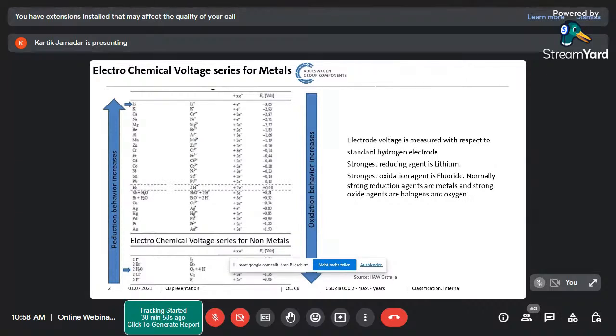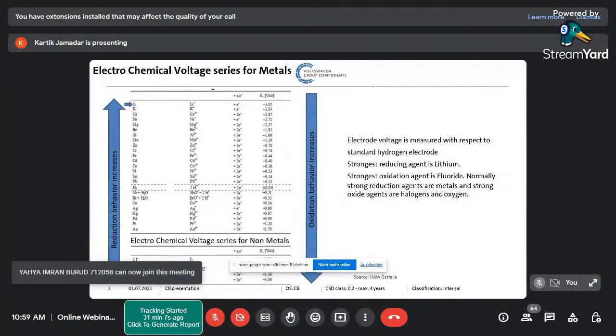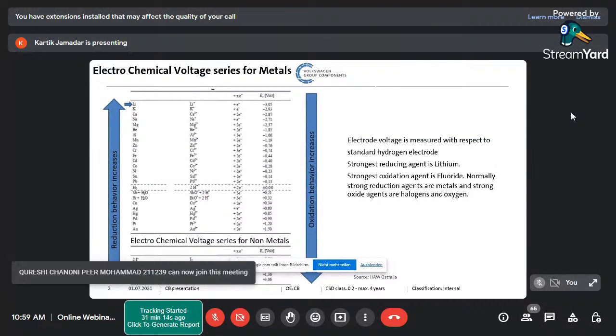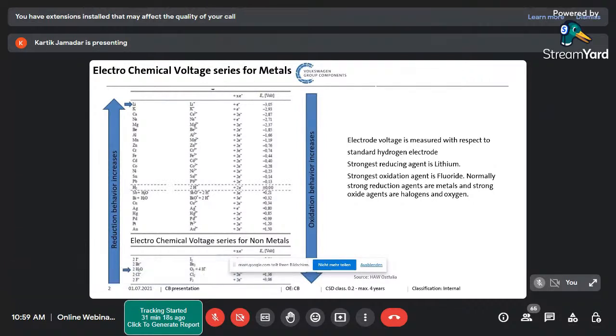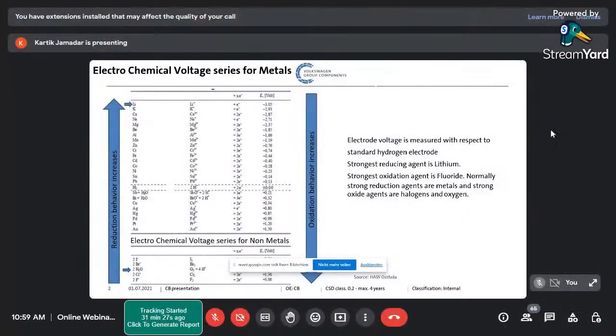At the same time, lithium, being a very lightweight material, has a good affinity for giving high energy. Lithium has the highest capacity in terms of energy. Normally, we say that one kilogram of lithium can give you around 12 kilowatt hours. No material can give so much energy. So lithium had a good potential. Luckily, we found a very good anode material and we want to stick to it. That is lithium. The main problem started happening on the positive side.